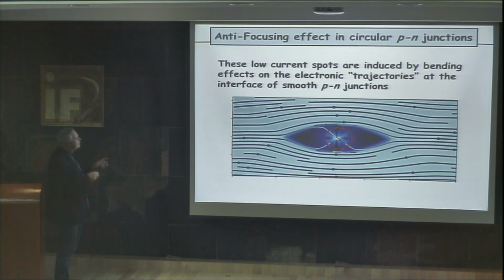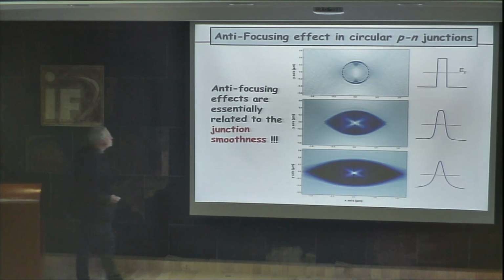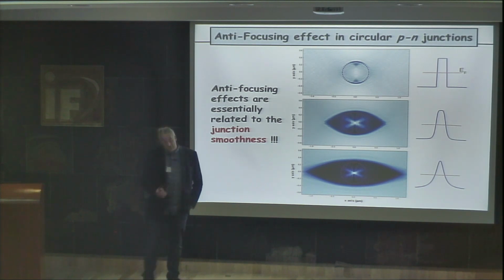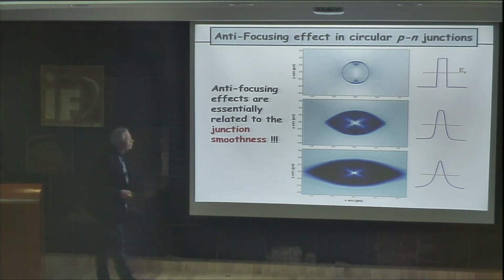So if you look at a semi-classical electronic trajectory, you have some bending of the trajectory along the p-n junction, and of course sometimes when you have a quasi-incident trajectory which is perpendicular to the p-n junction, then you can cross the system. And that's why you have a maximum here compared to the low values on the two sides of the lens.